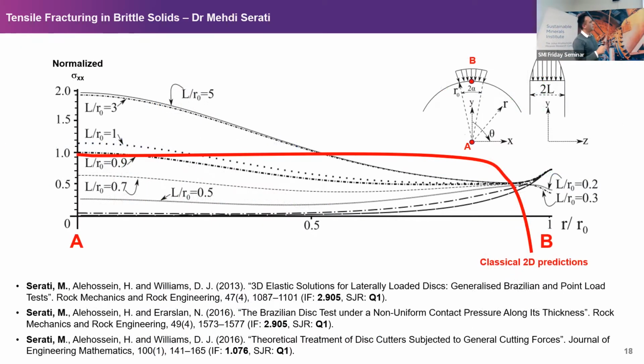And I think this is the interesting part. All right, so in a standard Brazilian test, it is assumed the contact angle is small, less than 15 degrees. The load is distributed evenly on the contact arc length and also along the thickness. And if you use that testing or boundary condition and put it inside the three-dimensional framework, the red solid line is the type of stress distribution that you get when you are moving from A to B. So this is a tensile positive regime. It means that the maximum induced, and this is normalized based on the Brazilian equation, it suggests that the maximum tensile stress, which is sigma XX, happens at the center. It's almost uniform all the way to 80% of the radius. That's why you get the Brazilian tensile rupture under a standard loading condition.